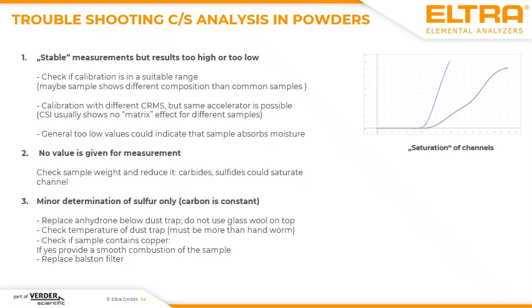You saw the example before, for example, that the dust provides a carbon content of 37%. Usually, an analyzer is not calibrated in this high range, but when you get stable results, but the expected carbon content is wrong, please make sure that you calibrate it in a correct range.